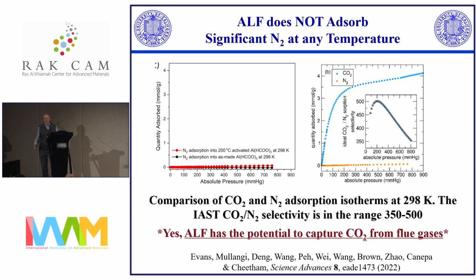It's extremely small. But nitrogen won't go into the cavity. And so when we take the two isotherms and look at the selectivity of CO2 versus nitrogen, it's in the range between 350 and 500. It's a phenomenally selective material. So yes, it does have the potential to do this CO2 capture from flue gases. And so by now, it's starting to get quite exciting, because if you're going to address a problem like CO2 in flue gases from a power plant, then